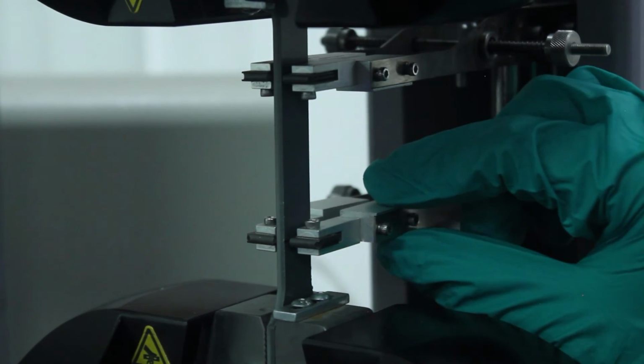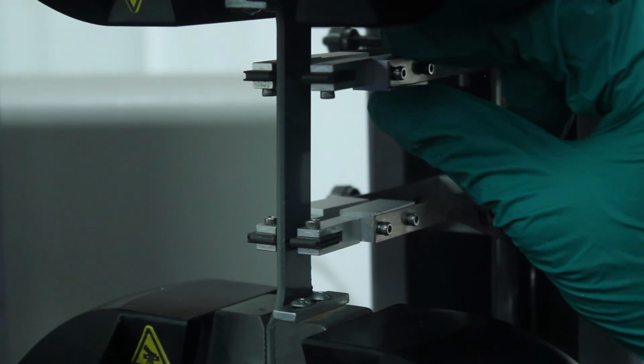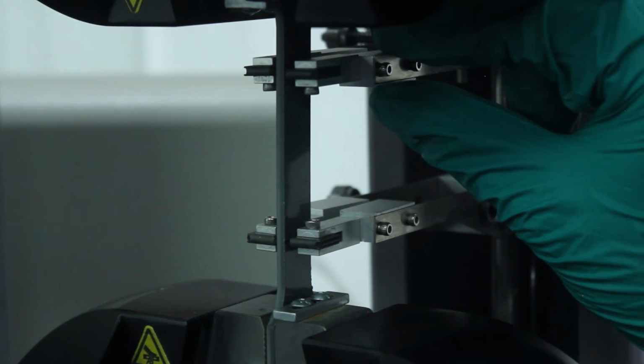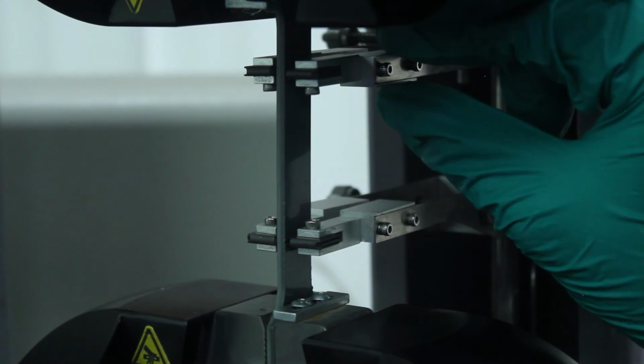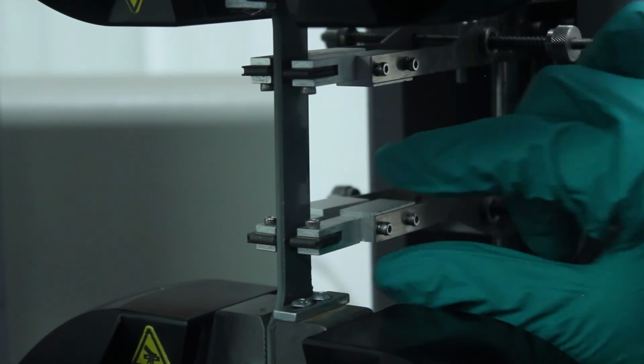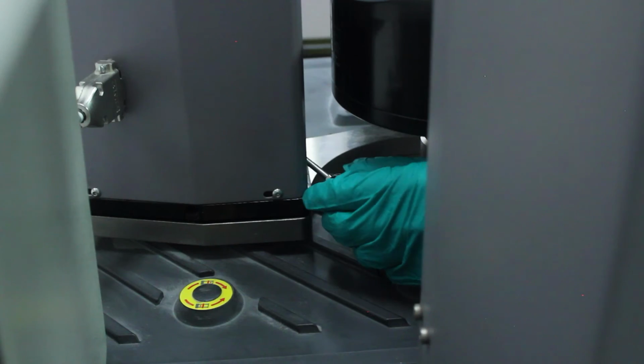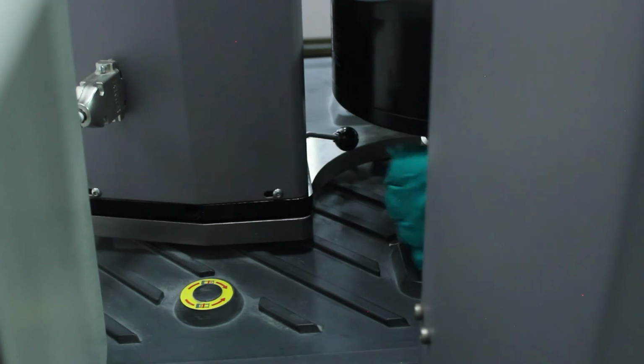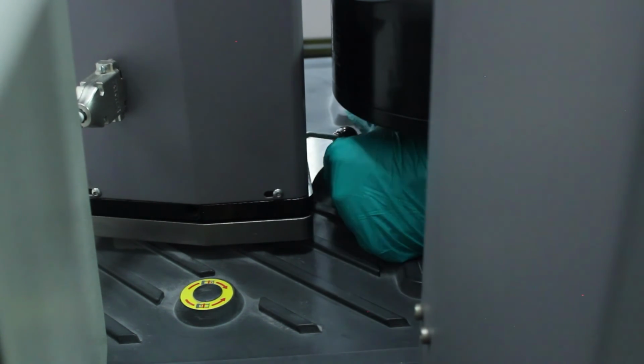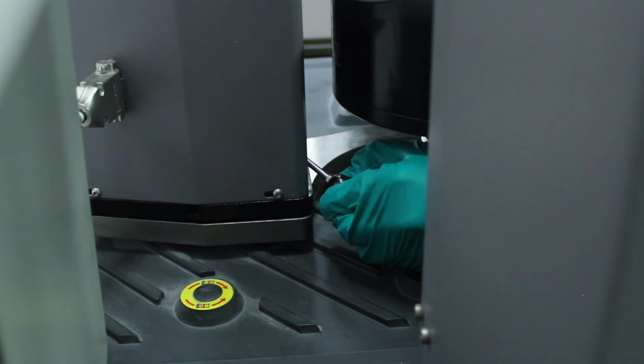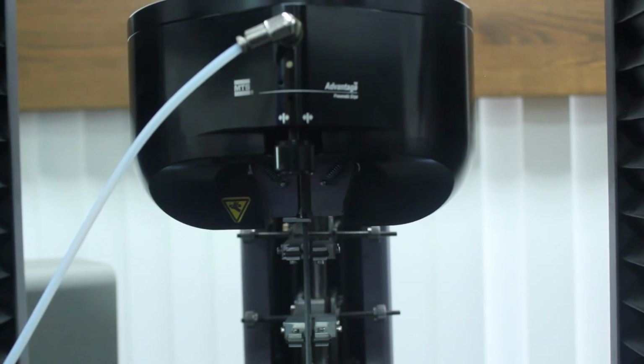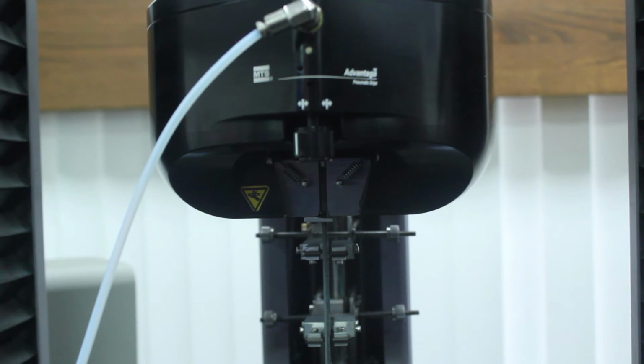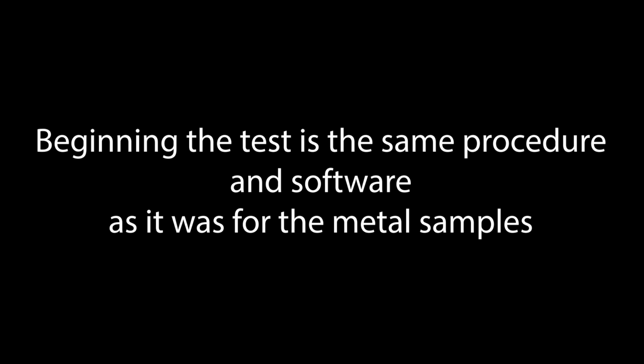When placing the extensometer on your sample, make sure the little black plastic knife edges line up with the Sharpie marks you made to indicate your gauge length. This alignment is easiest done with the extensometer closed. In order to open and close it, use a lever behind the bottom crosshead and turn it left and right. Once placed precisely, press the A button again to clamp the upper half of your sample.